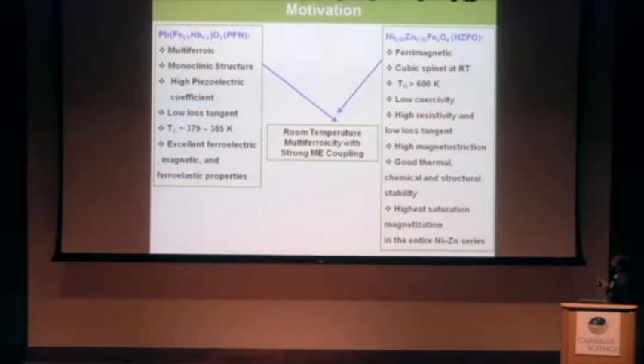And for the magnetic material, we have chosen nickel zinc iron oxide, as it is a ferrimagnetic material, and it has a cubic spinel structure at room temperature, and the Néel temperature is 600 K, so that the composite structure has magnetic ordering above room temperature, and it has low coercivity, high resistivity to withstand a high electric field, and a high magnetostriction coefficient. It has good thermal, chemical, and structural stability, and the composition of nickel 65 and zinc 35 possesses the highest saturation magnetization in the entire nickel zinc series.